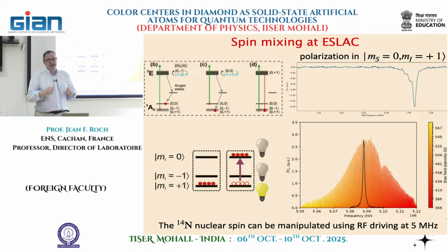Then what you can do is polarize again, by the same trick, a gas. And once you have a gas, or the species that you want, or the liquid you want, you can do NMR on that liquid, for instance, that would be much, much more efficient than the one that can rely only on the difference of population. So it's a way to optimize the nuclear spin polarization by using the diamond doped with NV as a resource, and then progressively transferring to the system.